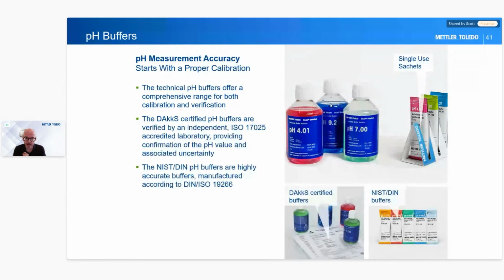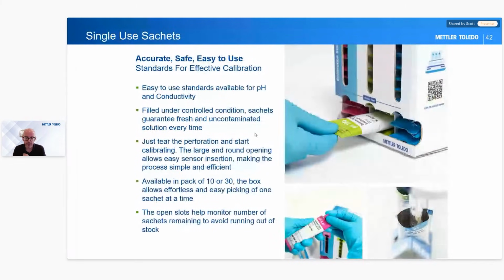So you've got to be really careful about which ones you select. At Mettler Toledo, we offer a technical buffer. So that has a calibration. You'll see it has a verification certificate to say this is the pH we've tested it at, which is fine. You may be in an accredited laboratory where you need to take account of accredited buffers. So we do a range of DAkkS certified buffers. They are independently tested by a separate laboratory and come with the ISO 17025 accredited laboratory's confirming certification. The other ones we do are NIST and DIN buffers. So it depends on what kind of measurements and what kind of system you use, but we also do NIST and DIN buffers in bottles and sachets.